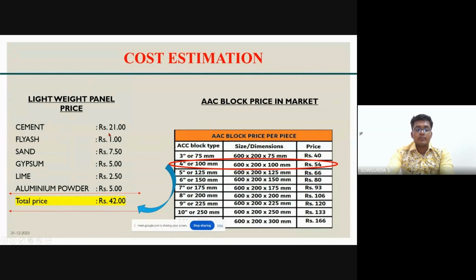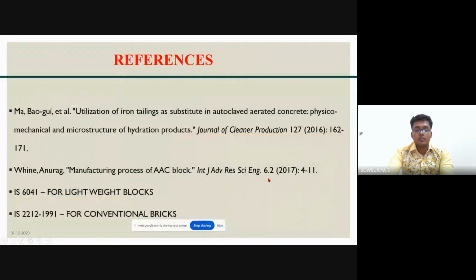The price of the cement is rupees 21 per kg, the fly ash is rupees 1 per kg, and sand is up to 7.5. This ratio is for one specimen, and the gypsum used for casting one specimen is rupees 5, lime is 2.5, and aluminum powder is 5. The total price of the block is 42, and the block available in the market is 54.